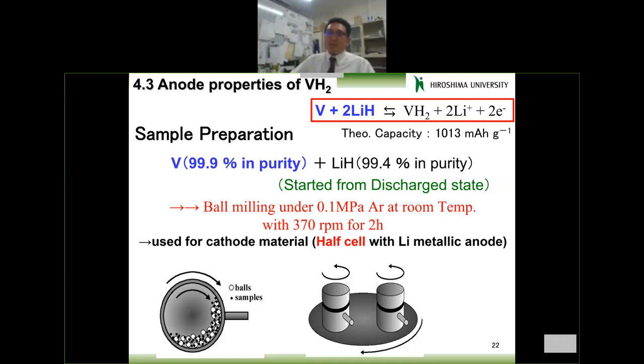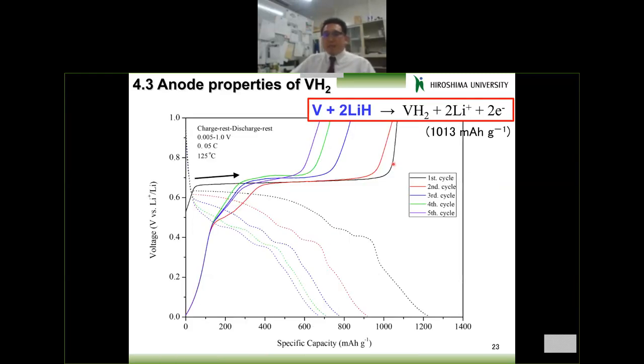So we started from vanadium itself. But of course, vanadium and lithium hydride is the lithiated state. So we started from this mixture, and with quite a similar method, we assembled the battery cell. And these are some charge-discharge properties. And of course, in this case, the lithium-including state was initial. So we start from here and then increase the voltage.